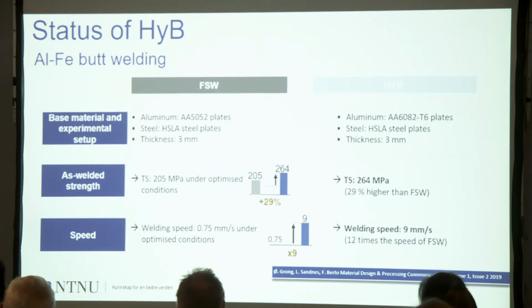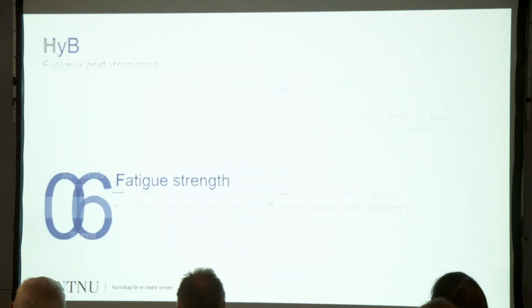About the aluminum steel welding, we have still better advantages. Here, in terms of strength, we have plus 29% more than friction stir welding, and the speed is multiplied times 9. So the speed of HyB is much higher than the speed of friction stir welding.